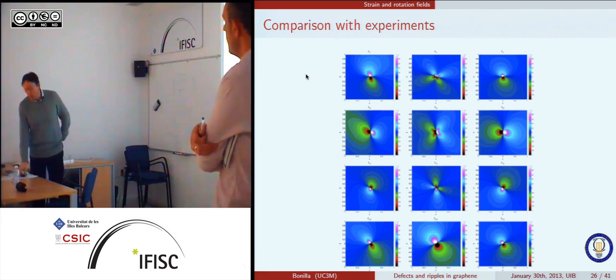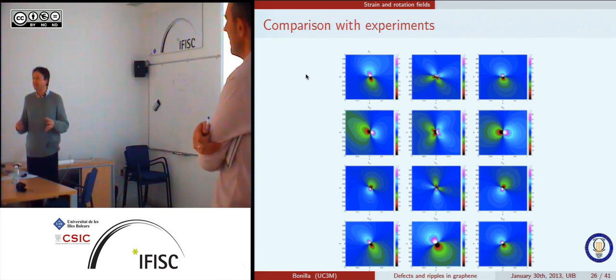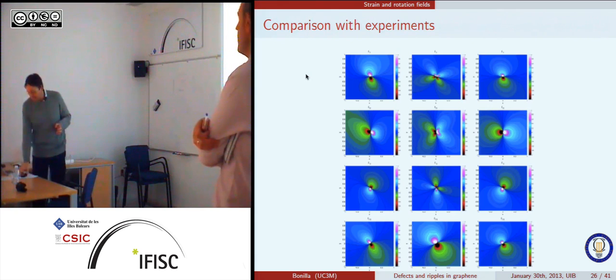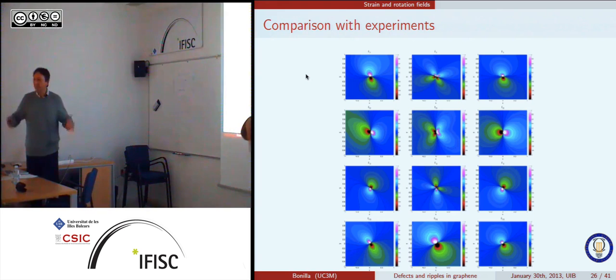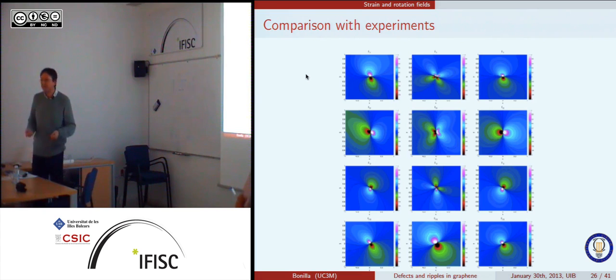But for instance, one way to control, not the ripples, but the wrinkles, the big ones, is you just take a graphene sheet like in a resonator, so you clamp it on two sides, and then you play with temperature. Now, it turns out that the expansion coefficient of the underground material where the graphene is pinned is different from the graphene itself. And then you are just inducing stresses into this, and that can create the wrinkles, or depending on how you do it, it can eliminate these wrinkles. So these are well-known experiments that do that. I think it was done probably 2009 or something like that by a different group of people.